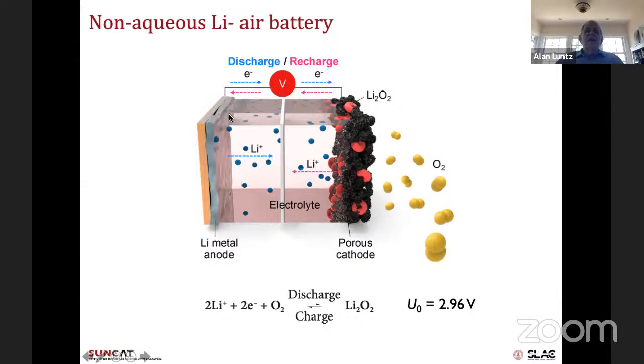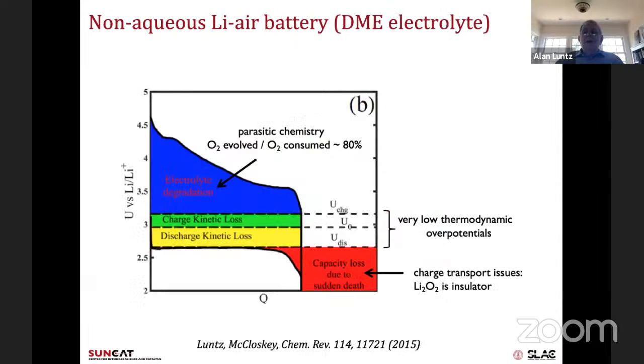What it is, is just a lithium metal battery, a porous cathode, and you take oxygen from the air and react it electrochemically to form lithium peroxide. And that gives a potential of about 3 volts. And then if you apply a potential higher than that, you can drive this reaction back the other way. It's a very nice electrochemical reaction. However, the problem is,